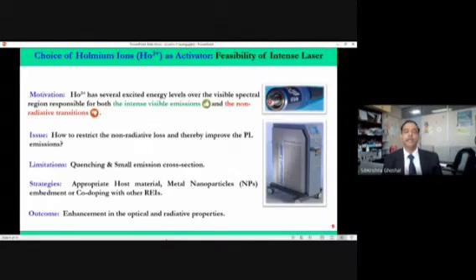The problem is that intense visible emission is okay, but the non-radiative transition is too high. Because if the non-radiative transition is high, it means the phonon will eat the photon. So phonons are the enemy of photons, and photons from the material will not come out. How can we eliminate the effects of phonons, which are responsible for the non-radiative decay? That is one of the challenges in these materials.